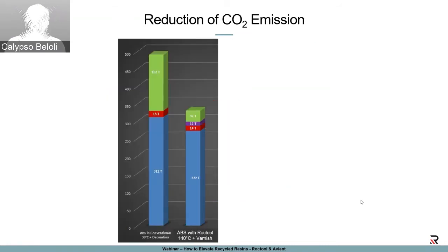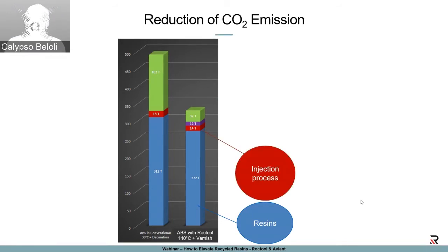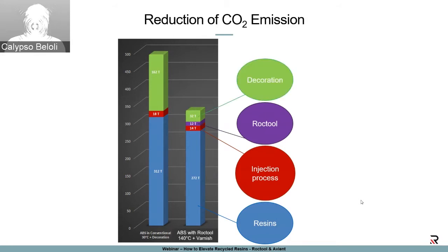So let's now compare with Roctool, same ABS, with only varnish, so no paint in this case. So you can see a reduction of the resin because we will reduce the scrap induced by the decoration process as we reduce the number of decoration steps. We reduce a little bit the injection process due to less parts molded, but we add the Roctool process, of course, and we keep a very small amount of CO2 emission from decoration.